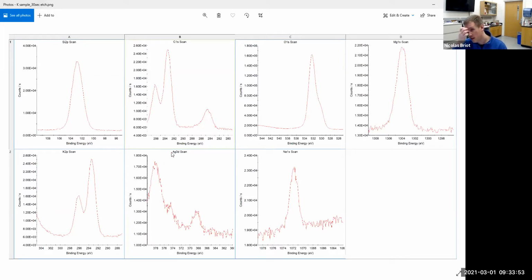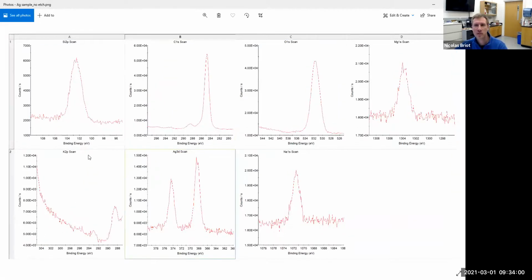So I did the same thing on the other sample, the silver sample, the yellow sample, before and after etching in the XPS system. Same idea here. We can try and compare what we see here with XPS and EDS. Again, you see silicon, oxygen, which is normal. You clearly see the silver, so obviously there is silver. We saw it in EDS too. We cannot see potassium. So no potassium here.